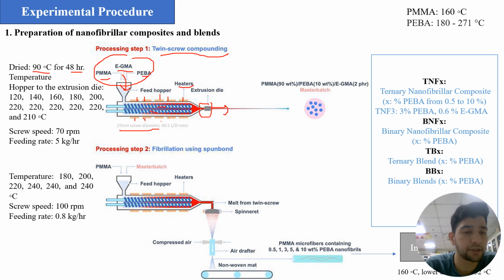So when we add these materials to the extruder, in this barrel the temperature goes from 120 to 220 and at the end 210 degrees centigrade. So at high temperature and mixing, it will mix and finally go out through the extrusion die. The resulting substance contains 90% PMMA, PEBA 10% and EGMA about 2%. It is not 2%, it is 0.6%.